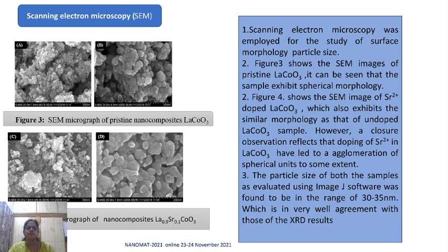Scanning electron microscopy was employed to study the surface morphology and the particle size. From figure 3, you can see the SEM image of the pristine LaCoO3. From this image, you can see that the sample exhibits a spherical morphology, while figure 4 shows the SEM image of Sr doped LaCoO3, which is similar to that of the pristine LaCoO3 material.